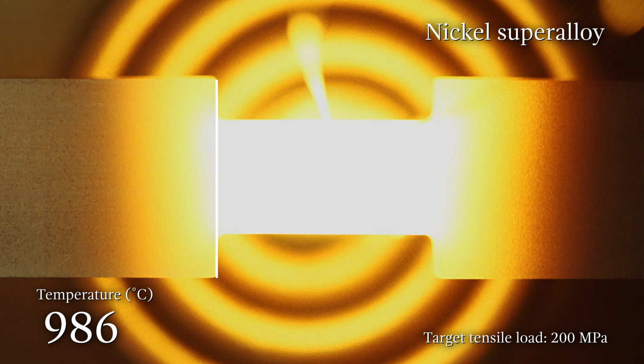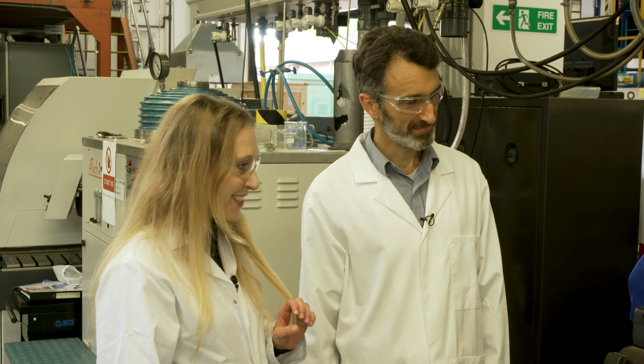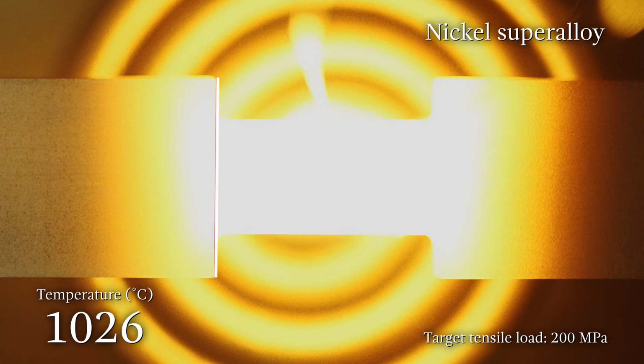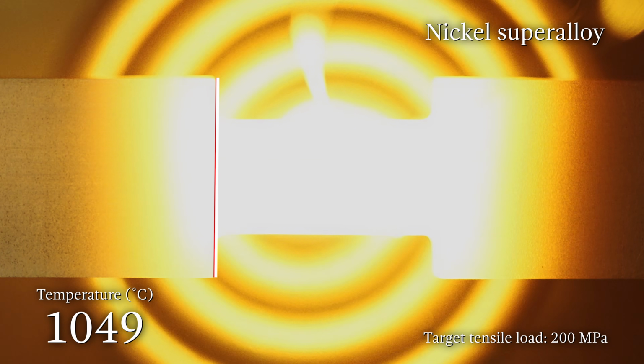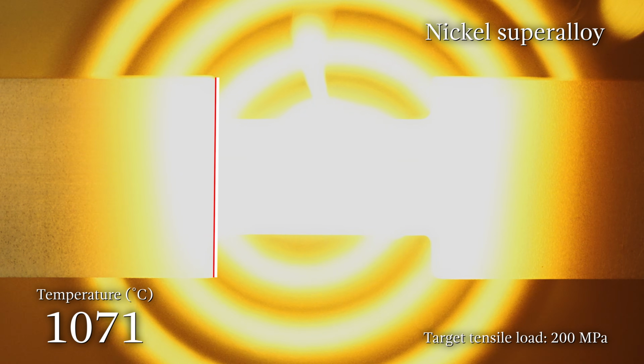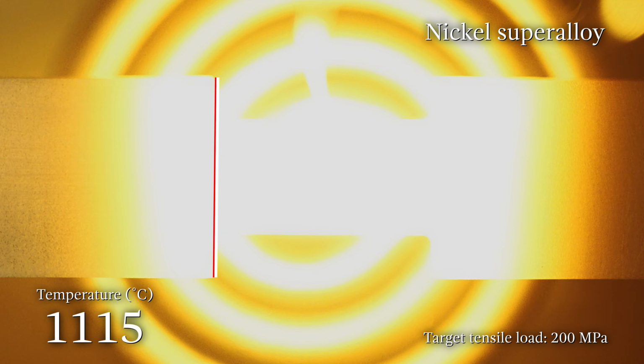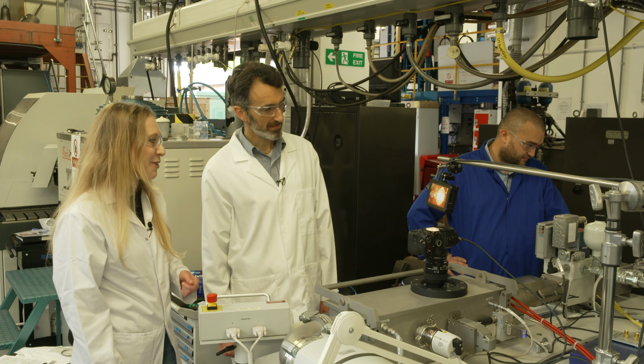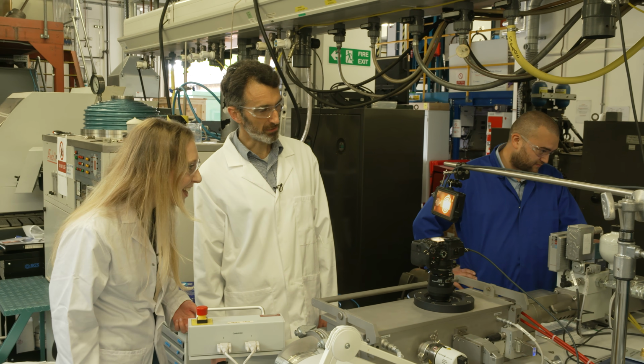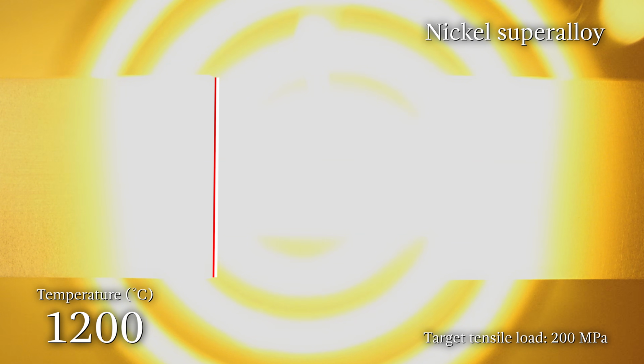And in our test, you can see exactly how that plays out. 1,000 degrees and still nothing. Still nothing. There we go. Oh my gosh. That's 1100 degrees C. It's stretching. I mean, it's still holding up. It's doing a good job. That's 1200 degrees C. 1200. That's when the temperature program has stopped. And it's still surviving. Still going.